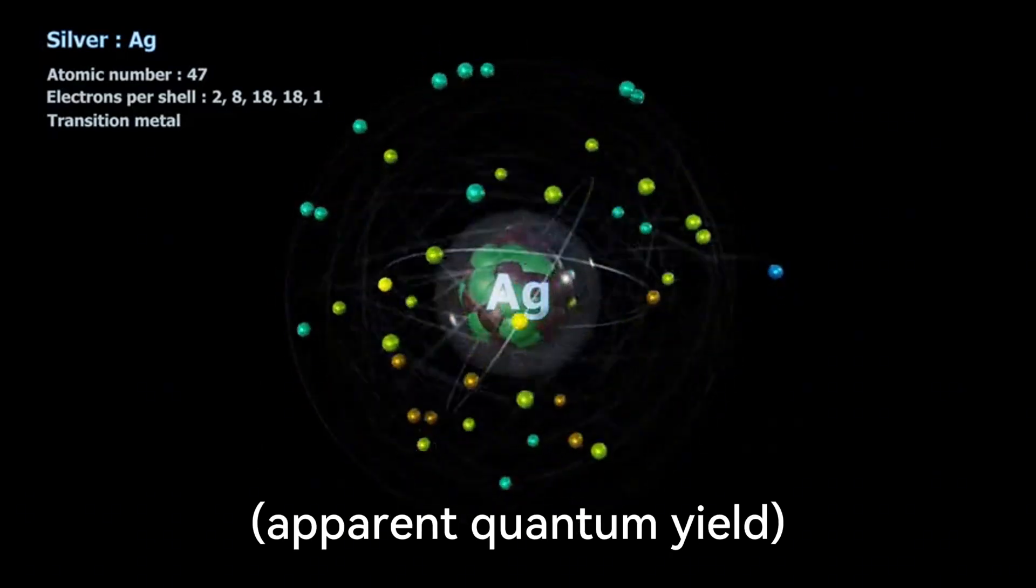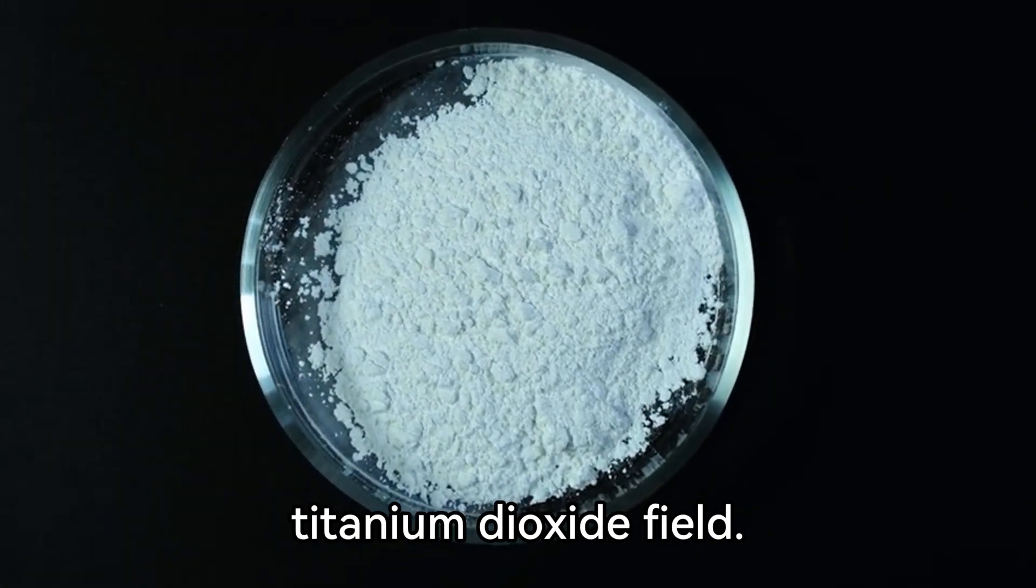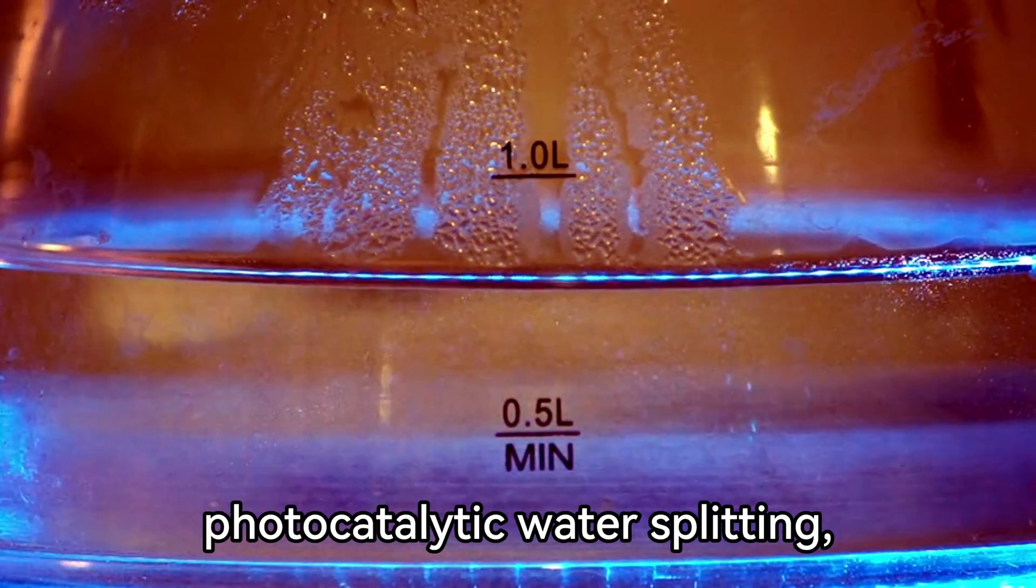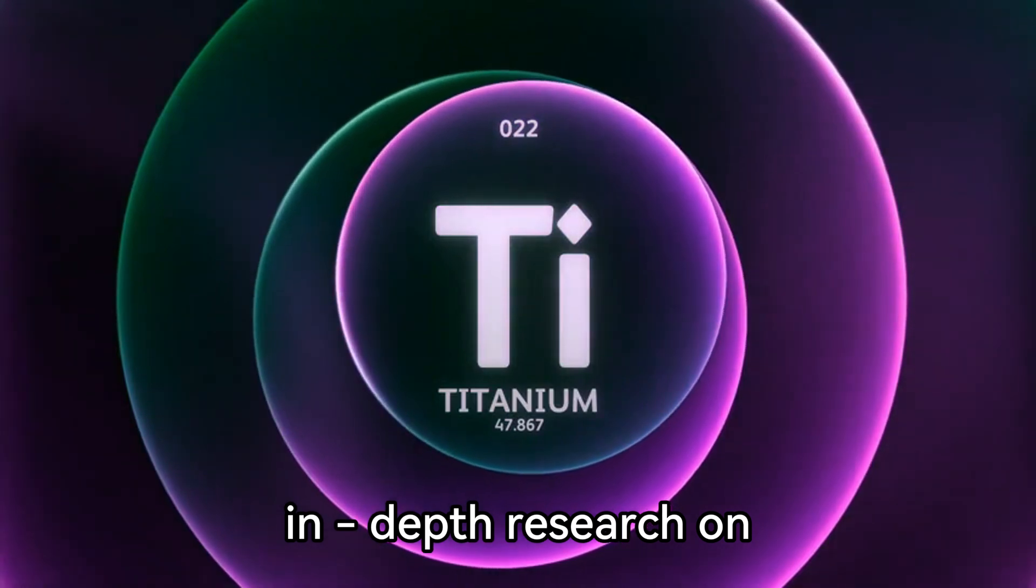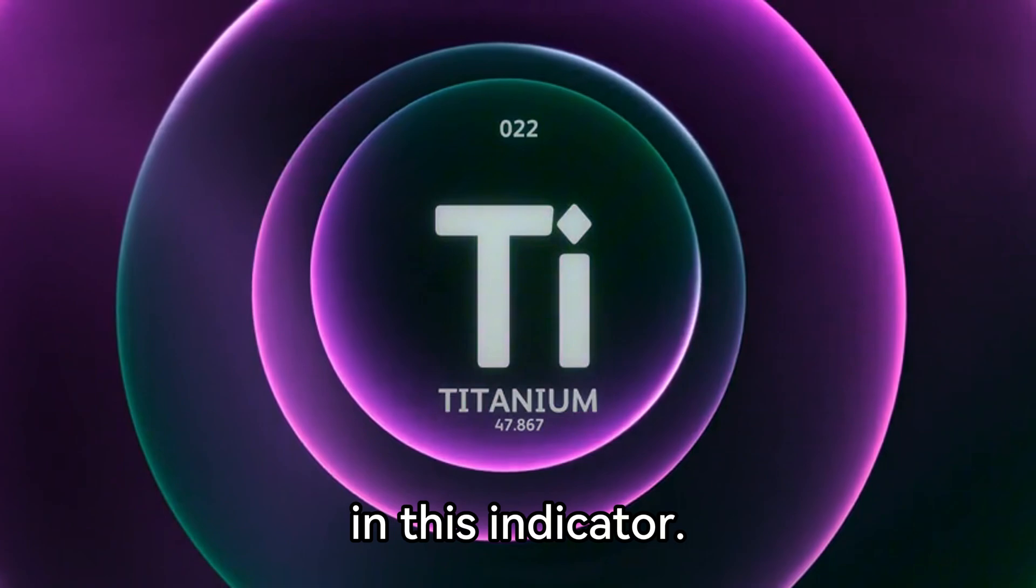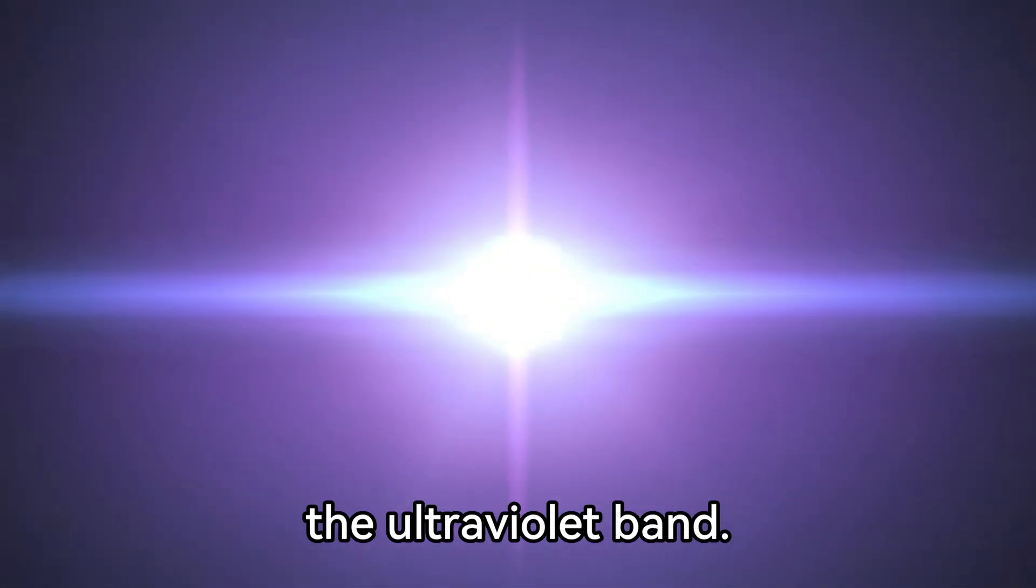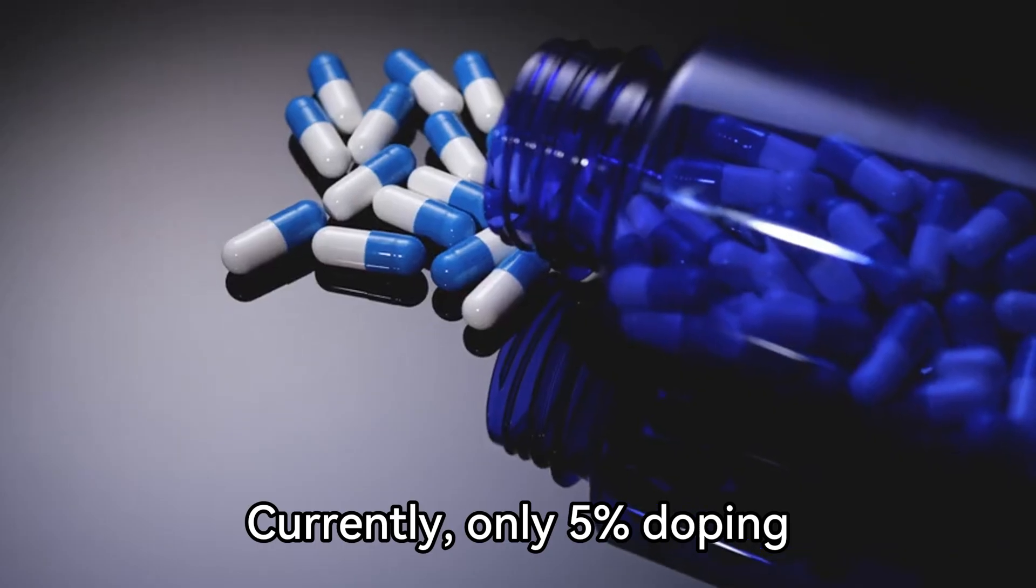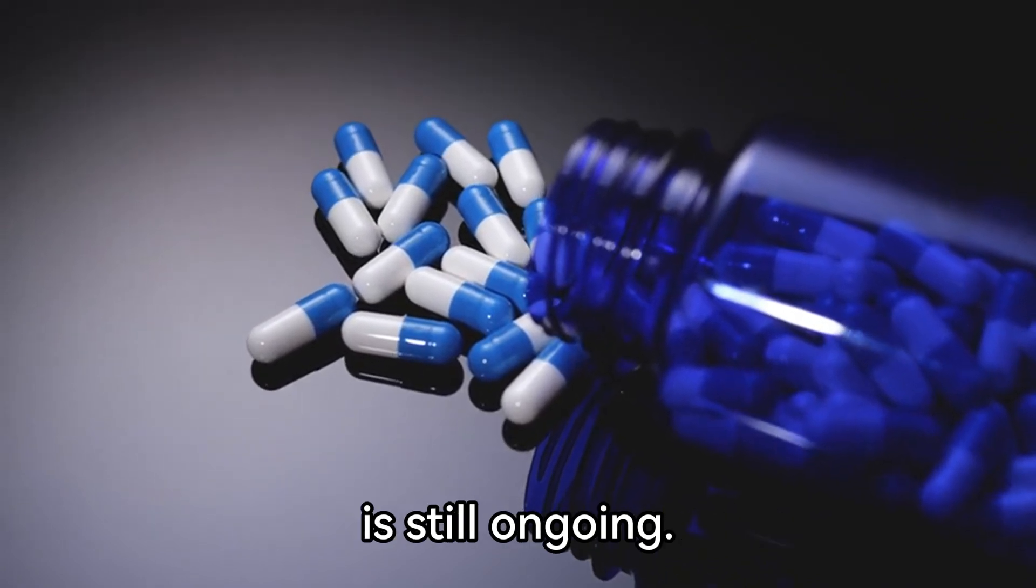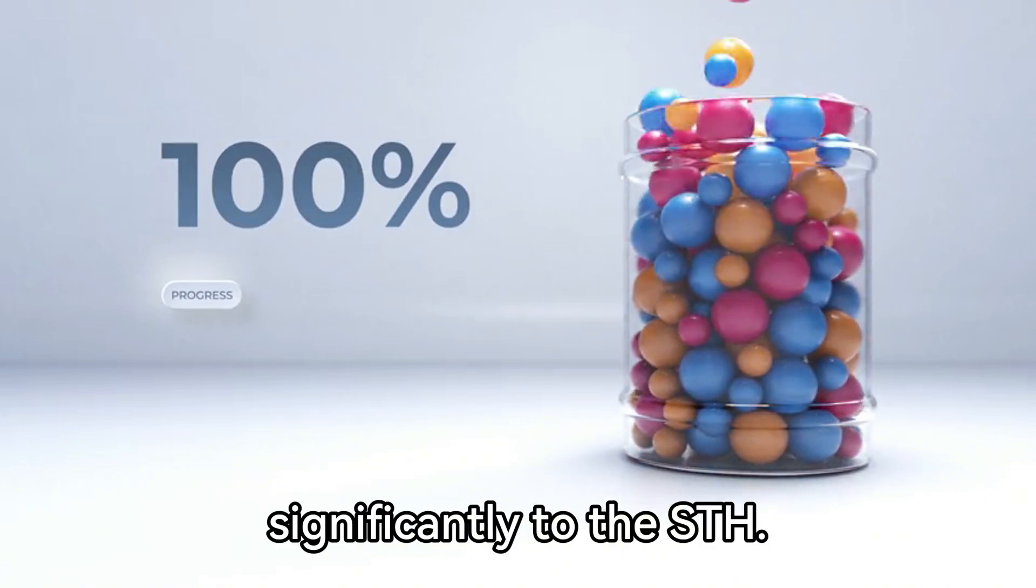The first is the AQY apparent quantum yield mentioned earlier. Currently, it has exceeded 30%, which is already very high in the titanium dioxide field. However, in the entire field of photocatalytic water splitting, it is not the highest. Some catalyst designs can achieve several tens of percent. If we continue to conduct in-depth research on titanium dioxide, there is still room for improvement in this indicator. Essentially, it refers to the utilization efficiency of photons in the ultraviolet band. Through further doping and regulation, there is hope for further increasing the AQY. Currently, only 5% doping has been used and the research on its mechanism is still ongoing. If the AQY can reach over 90%, it will also contribute significantly to the STH.